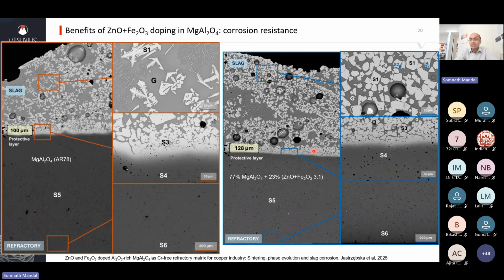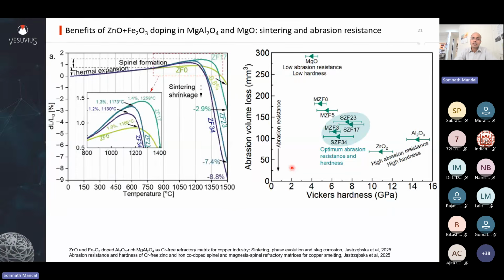So the takeaway message is that for zinc and iron doping, you want more zinc and less iron, because iron you don't want a lot of, it will form liquid phase. So 3:1 is a good ratio, and then 23% of this mixture was added. One of the other benefits other than the protective layer formation is that zinc and iron doping at 3:1 gives you better sintering of the matrix, and you get to densify your matrix better, and a denser, smaller pore size matrix is always beneficial for corrosion resistance.